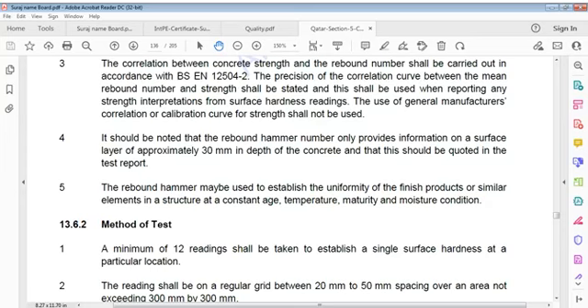Again I say, it should be noted that rebound hammer number only provides information on surface layer of approximately 30 mm in depth of concrete, and that this should be quoted in test report. Rebound hammer may be used to establish uniformity of finished products or similar elements in a structure at constant age, temperature, maturity and moisture condition.